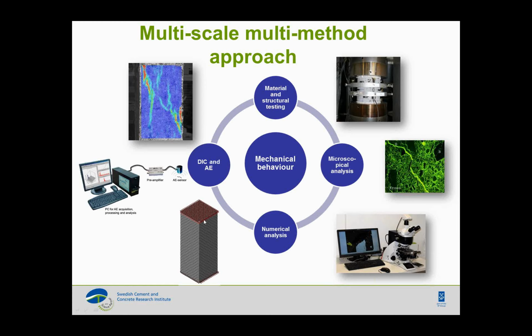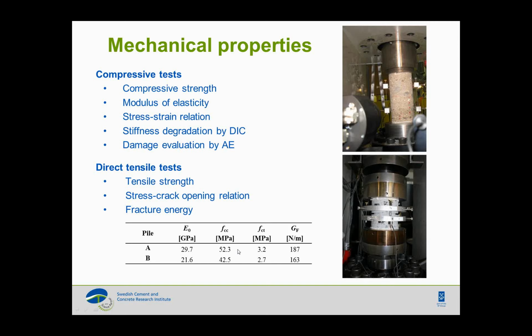We also did a direct tensile test to have a value for the strength, but also to have a stress-crack opening relation, which is a direct input to our analysis, and we also looked into the fracture properties. So down here in this table we have pile A, the mildly damaged one, with the elastic modulus on average about 30 gigapascal, compressive strength of 52 MPa, tensile strength of 3.2, and fracture energy of 187. And then I move forward to the next slide here.